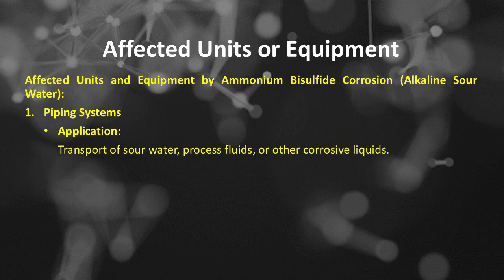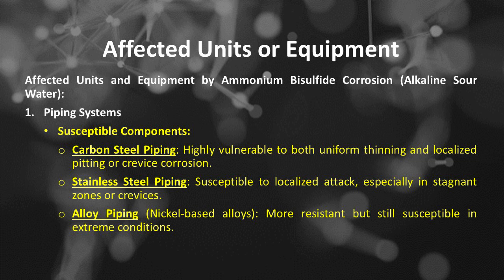Affected units and equipment by ammonium bisulfide corrosion or alkaline sour water include, Number 1, piping systems. The application of piping systems is to transport sour water, process fluids, or other corrosive liquids. The susceptible components of piping systems include carbon steel piping, highly vulnerable to both uniform thinning and localized pitting or crevice corrosion; stainless steel piping, susceptible to localized attack, especially in stagnant zones or crevices; and alloy piping, nickel-based alloys more resistant but still susceptible in extreme conditions.